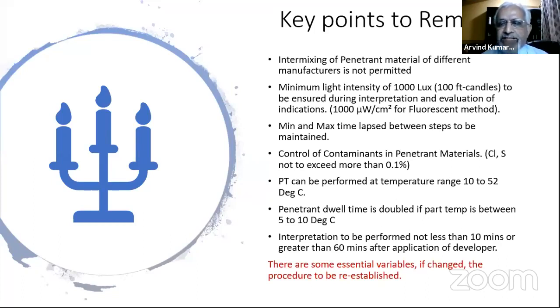The minimum light intensity, as I said, has to be 1000 lux for visible method and 1000 microwatt per centimeter square for fluorescent method. Now, other important things which did not appear in the slide, but I mention here, is minimum and maximum time lapse between the steps. This has to be established.